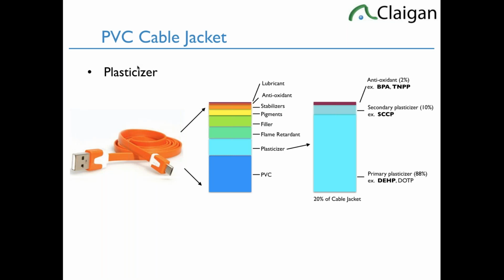So short-chain chlorinated paraffins are called secondary plasticizers, but they aren't actually plasticizers. They enable orthophthalates to be more compatible with PVC. There's a number of advantages in that. One, they don't migrate as much out of it. But one of the other big advantages is it's cheaper. So DEHP, or most orthophthalates, are about $1,300 per ton. The replacements, terephthalates like DOTP, are very similar in price. One of the reasons why terephthalates are a common replacement for orthophthalates.